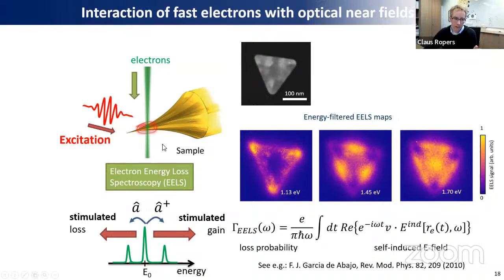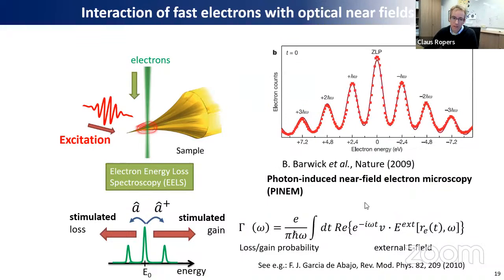So what's relevant both for electron energy loss and for this process is essentially the scalar product of the electron velocity with either the self-induced field, so the field produced by the electron itself acting back on the electron, or by the external field. When you Fourier transform it, you get the electron energy loss spectrum or this photon-induced near-field electron microscopy spectrum. So if you don't just look at the spontaneous loss but at the stimulated loss, you can not only have spontaneous scattering to lower energies, but also get electron energy gain by the electrons picking up energy from the light field.